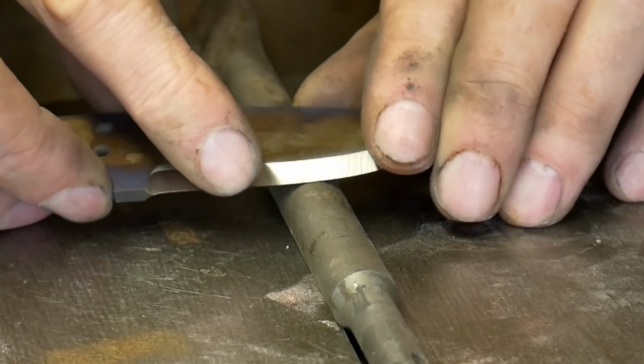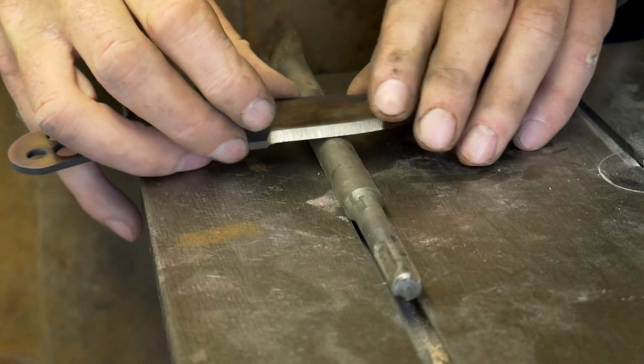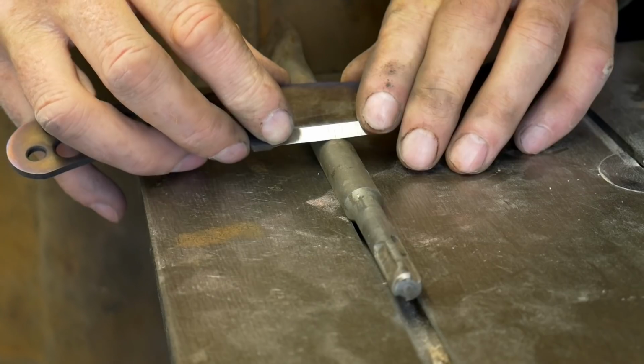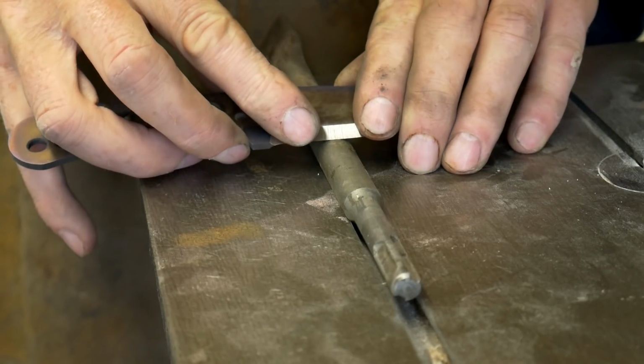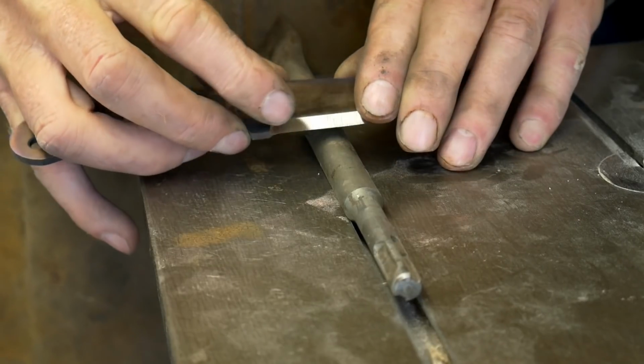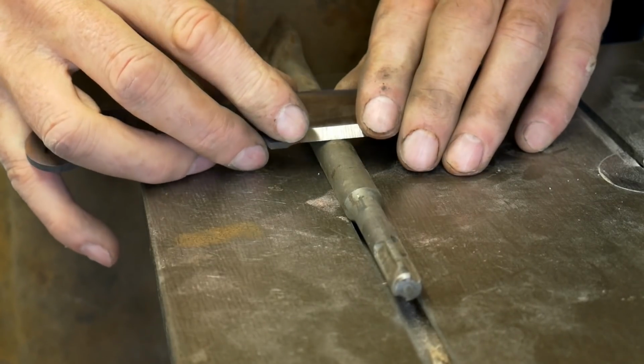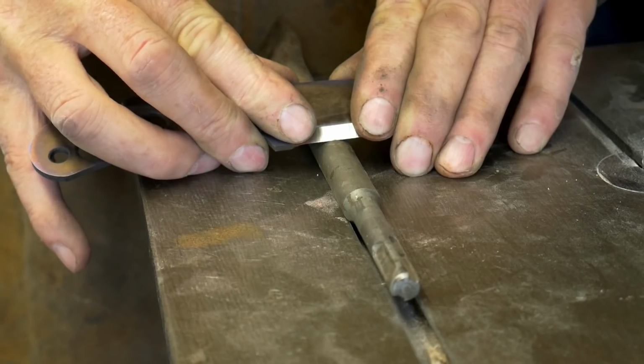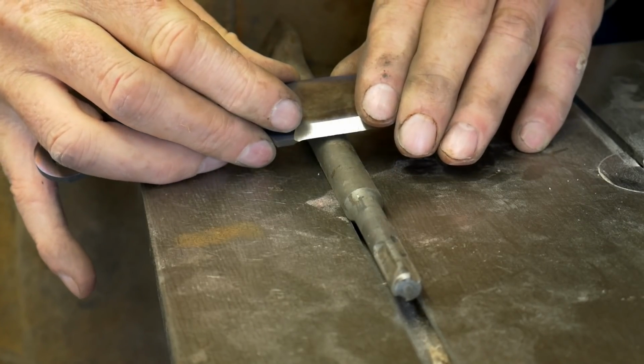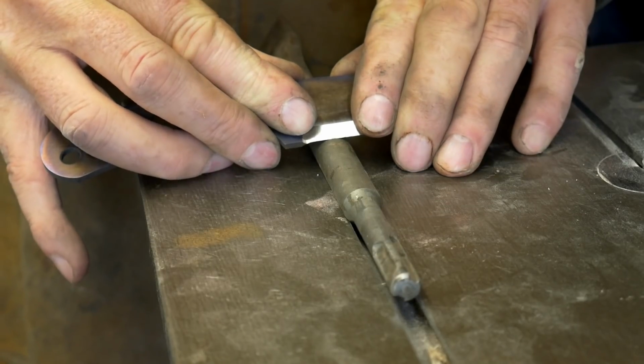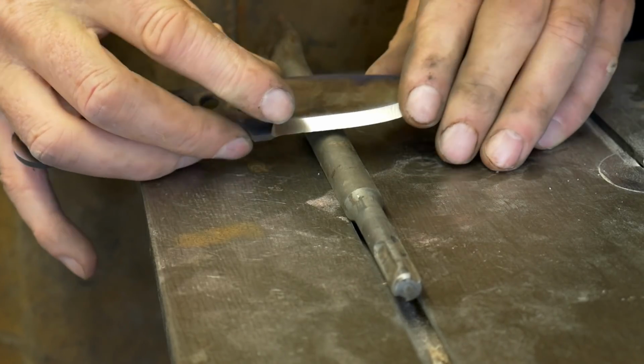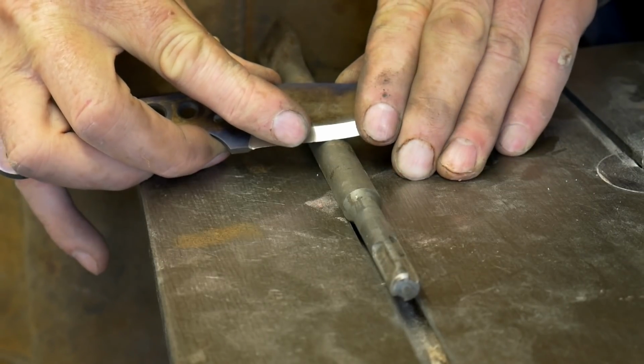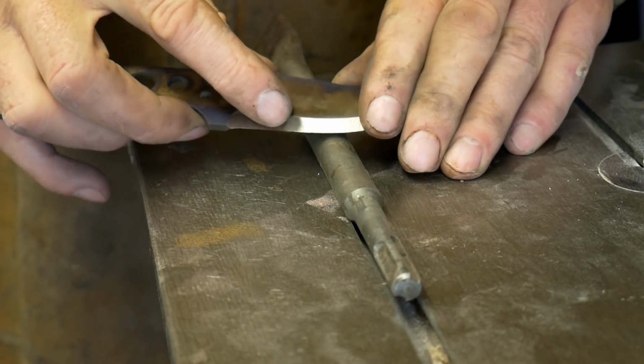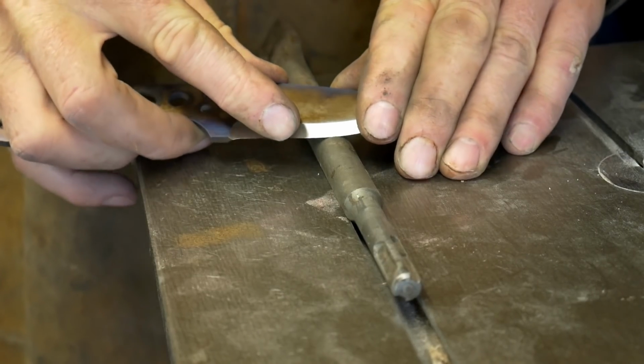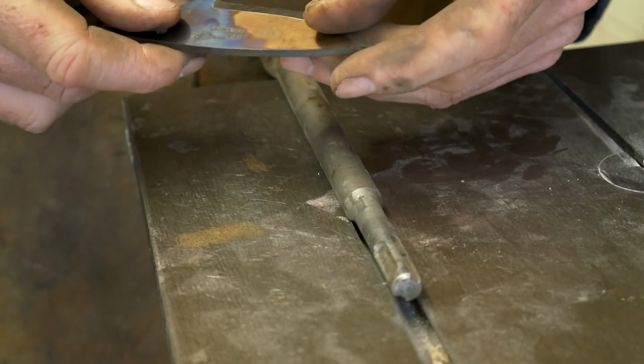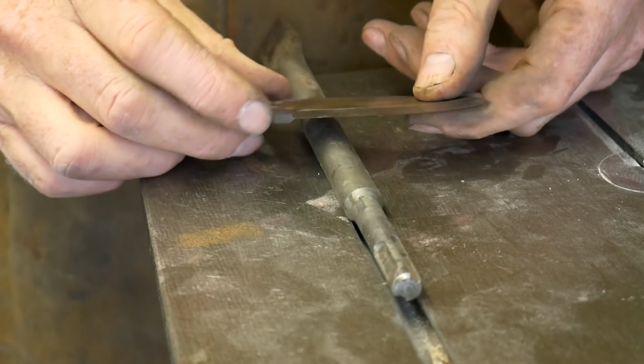That's a good indication. But if I push hard enough and increase the angle above the bevel, I can make the blade fail. And it's taken a lot of pressure to do this. And that edge is failing. It's failing to a roll, which is ideal, because a roll is very easy to fix.